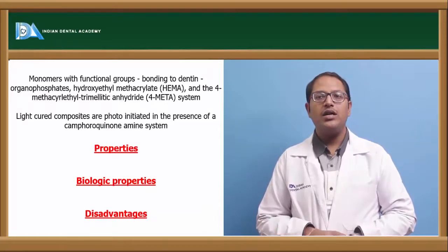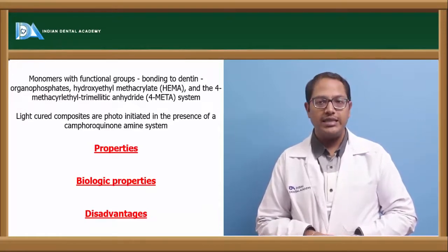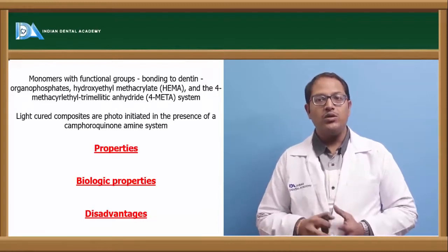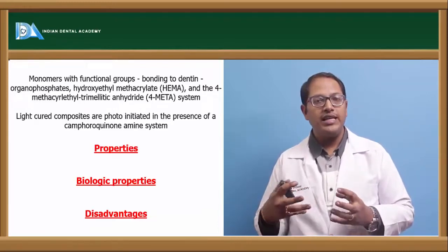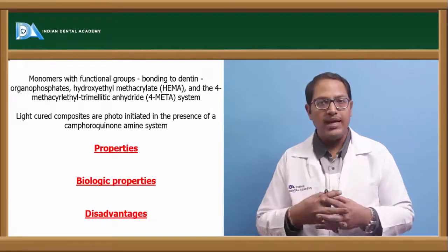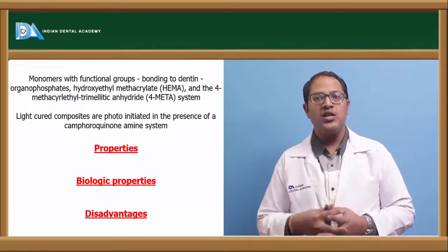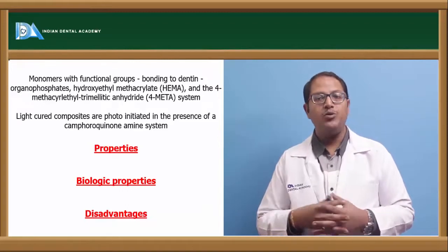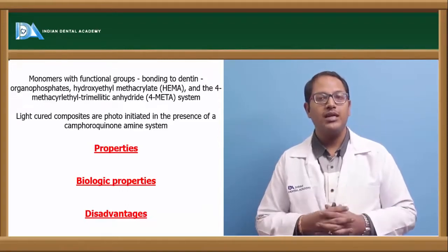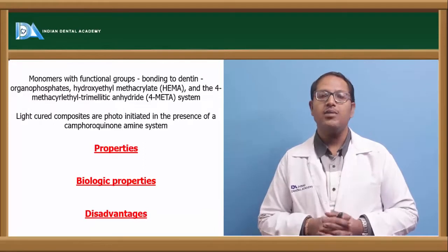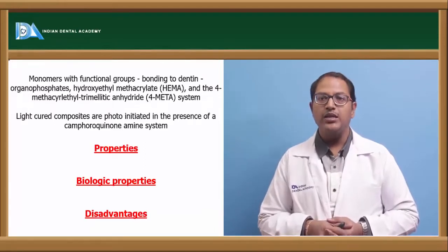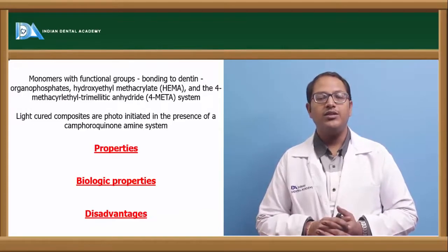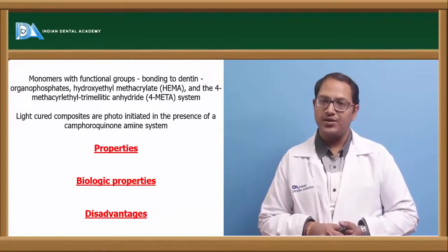Now this interlocking is with the partially demineralized dentine by infiltrating into the etched dentine. So what happens when this infiltrates into the etched dentine, the micromechanical bond is getting stronger. So it forms a chemical bond to the composite restorative material and porcelain and shows a good micromechanical bond strength to the sandblasted base metal alloys as well. For noble metals, they show a chemical reaction with that of the oxide layer on the metal surface which is